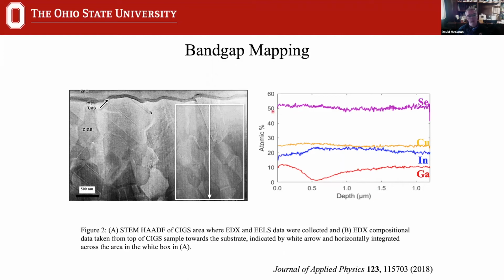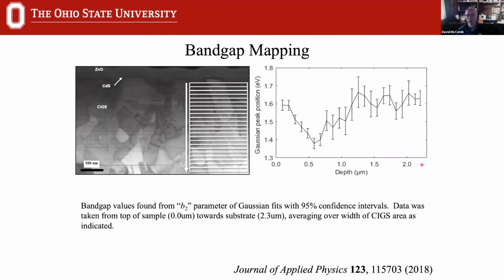And in particular, what we want to do is go across this large area of this full device. This is the compositional profile, just over 2 microns in terms of the scale of the device, and this is the composition. And now what we want to do is go across here and map the position of the band gap. And this is what we've done here. We measured this from the B parameter of the Gaussian, which we fitted within some confidence levels, and then we're plotting the position of that peak over that 2 micron device.